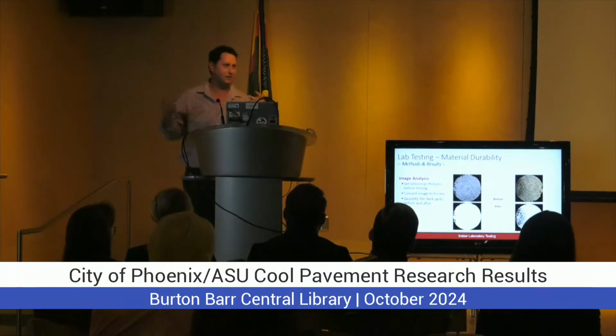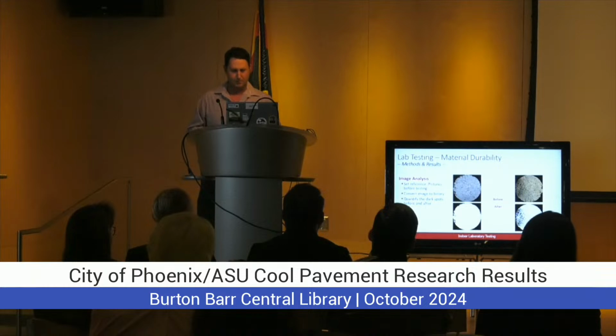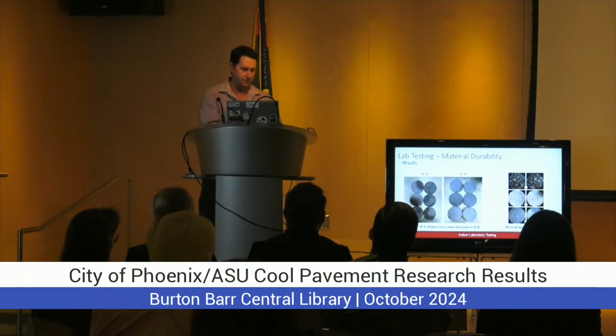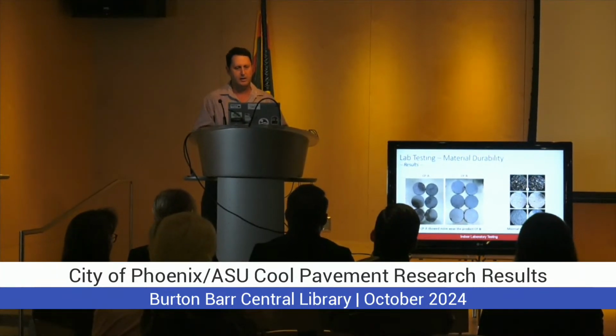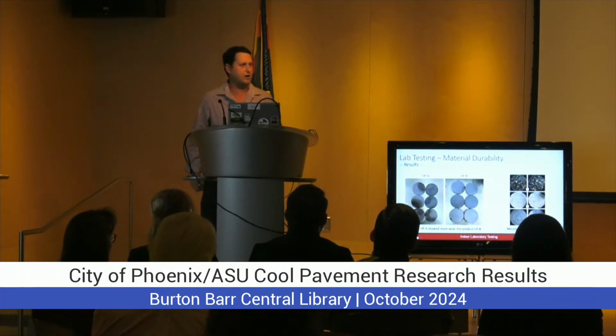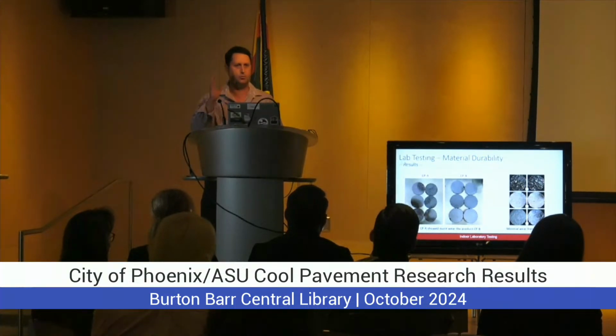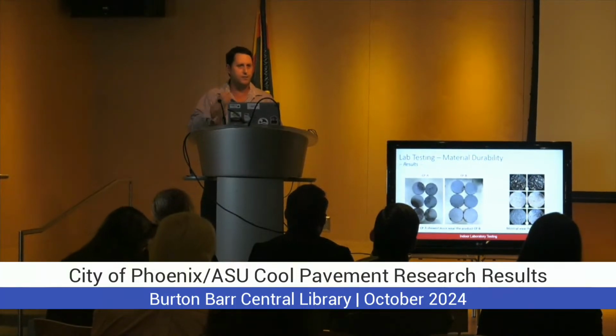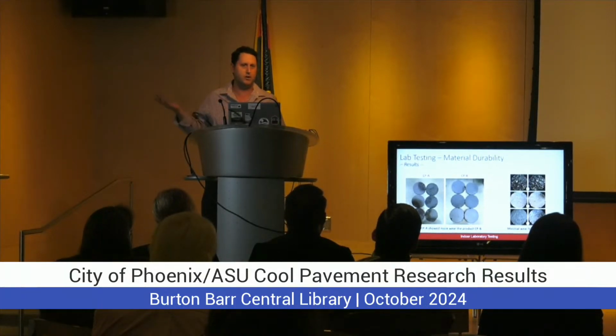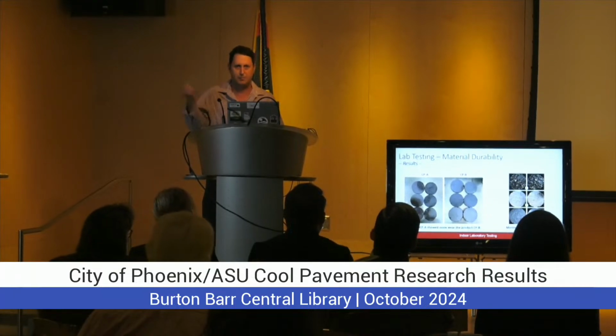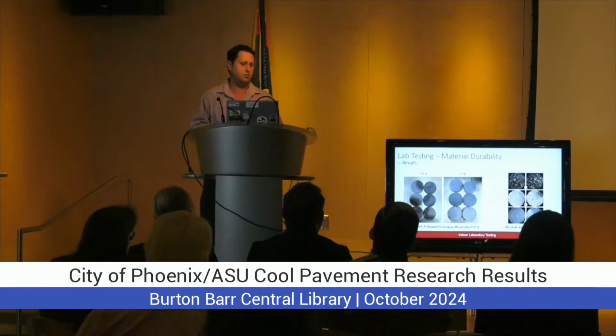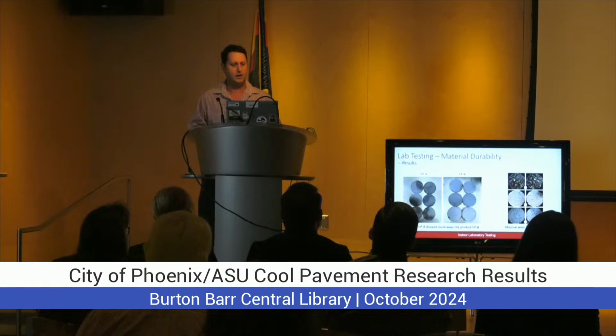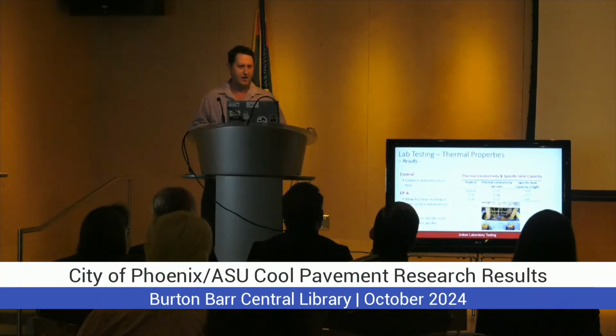Again, these methods are in the exploratory mode. We still need to refine them. But basically, what we have from the lab samples is that usually product A wore more than product B. This can be due to different curing times, the way of application. The other feature that we see on the right is our field cores. For all of the field core samples, we see minimal wear. And it can be due to the different texture, the application. When we cored these samples, they had already been in the field like 2-3 months or maybe longer, so they got more time to cure, to bond. But these are the questions that we need to start asking and see how we can evaluate this type of coating for future application.